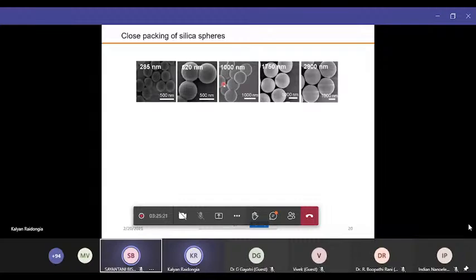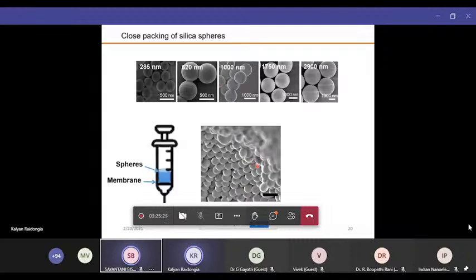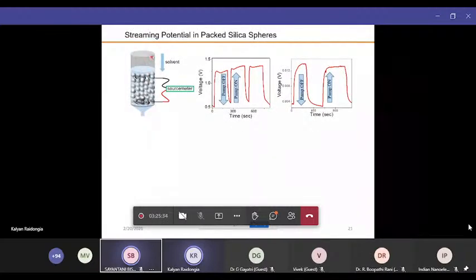Then once we made these different sizes, we pack them in a syringe, and in the syringe itself, between the spheres, we put two electrodes, copper wires, and we started pushing liquid through this. And as soon as we push liquid through this, we can see a good amount of voltage, around 120 millivolts to 150, which is almost 100 times more than what we got with the highly tight nanofluidic channels. This is a large improvement.